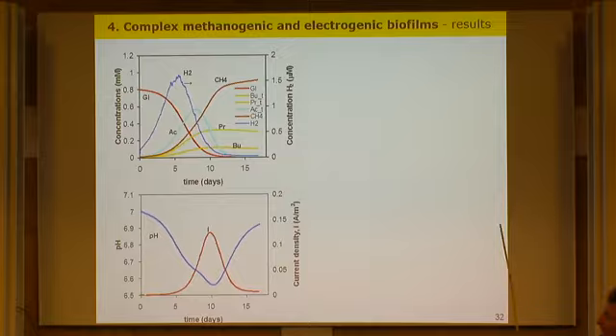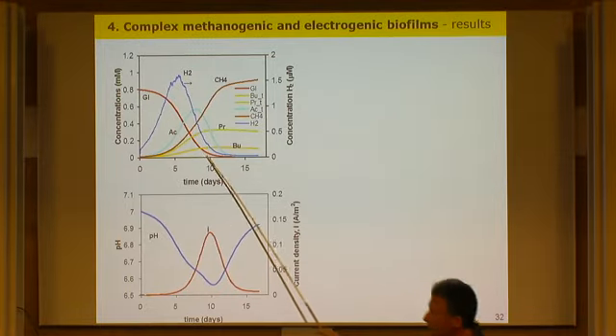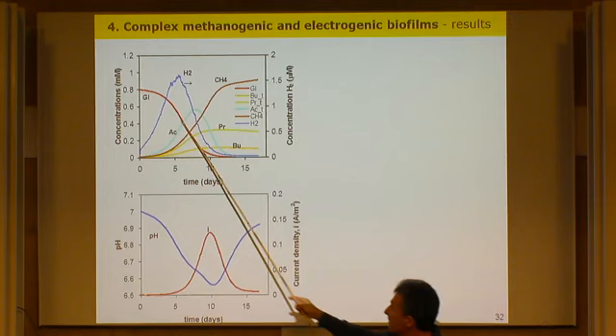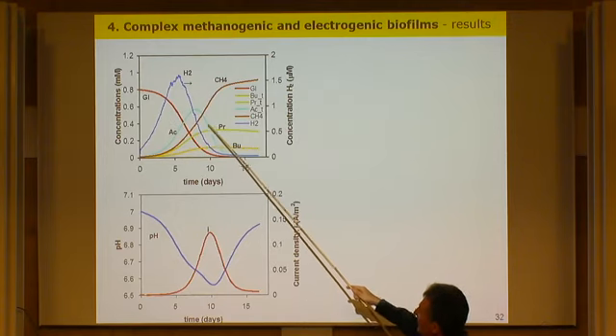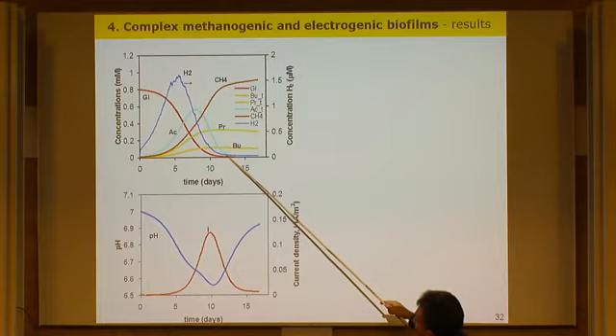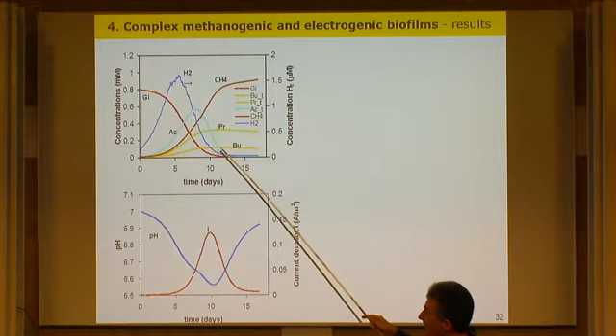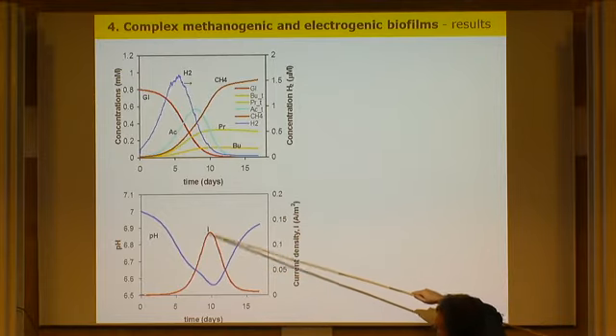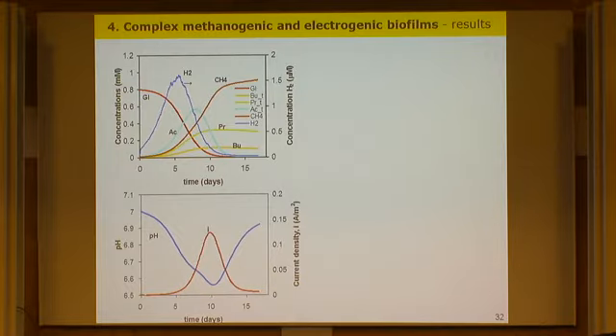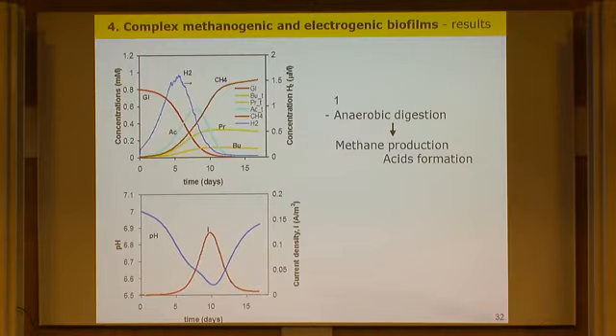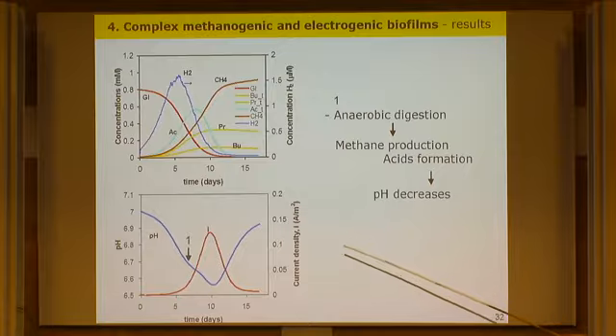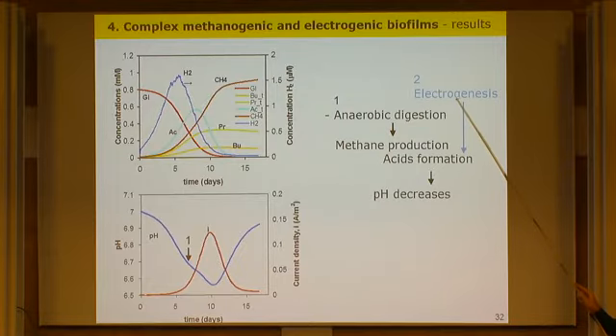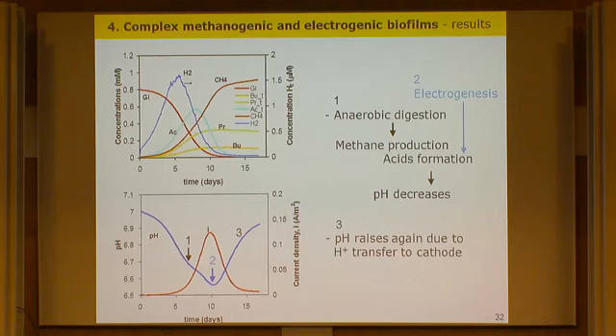Okay, so going back to the current production, you see the typical phases for anaerobic digestion. This is glucose consumption. You produce here acetate, propionate, butyrate, but then acetate is consumed by the electrogens. And this coincides with the current production here. And pH is also interesting here. So first you have the anaerobic digestion, you form methane, you produce acid, the pH decreases, so it's acidified. And then you have the electrogenesis from acetate as a second step, and then you have a further dip in pH, because this also produces some protons.